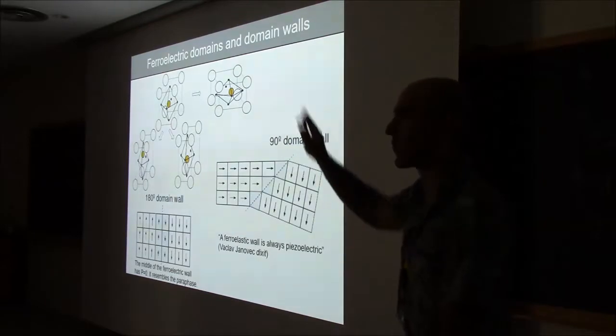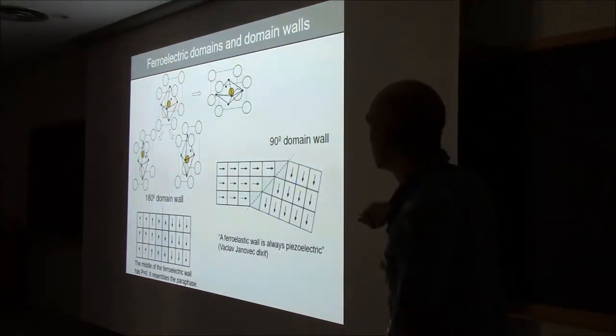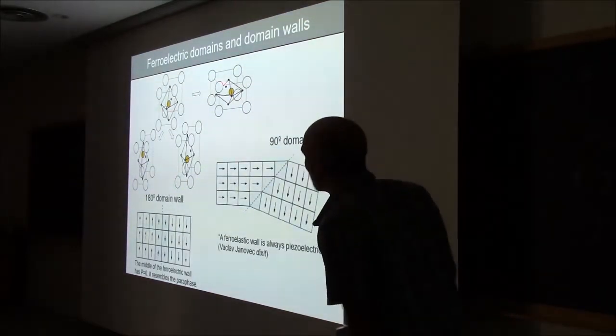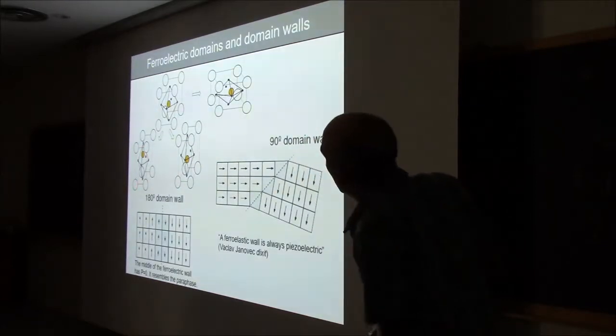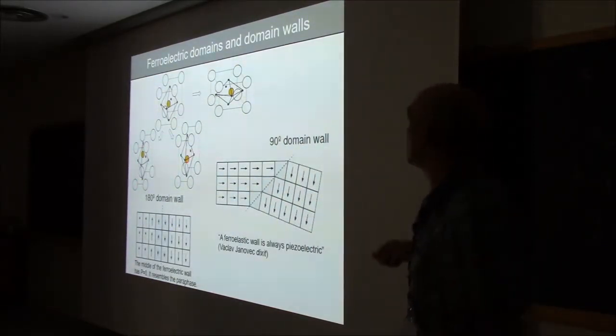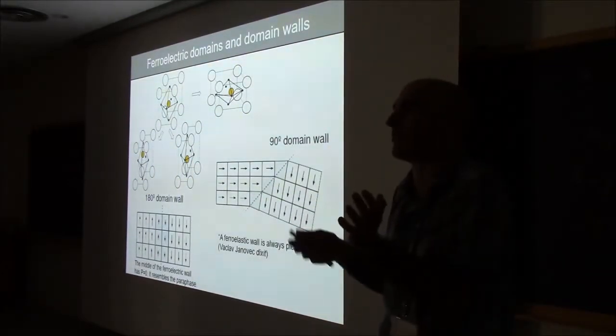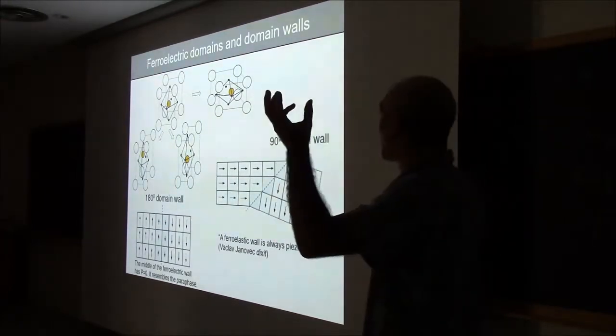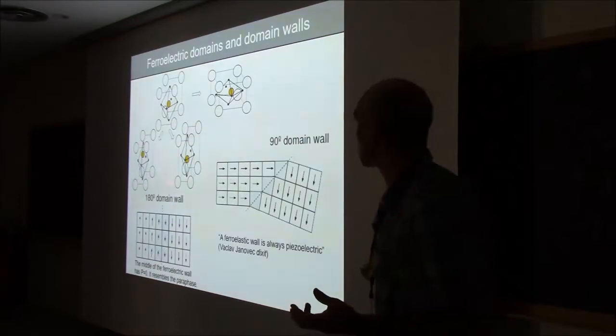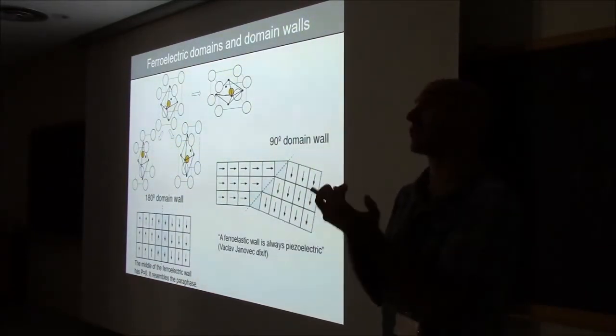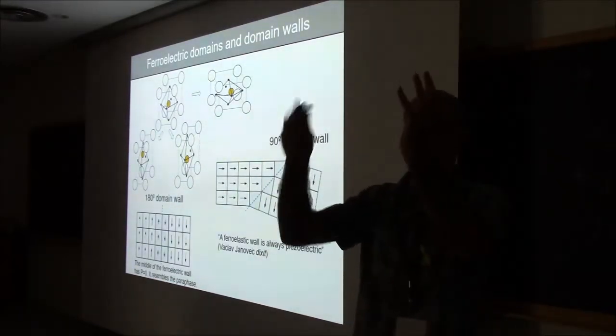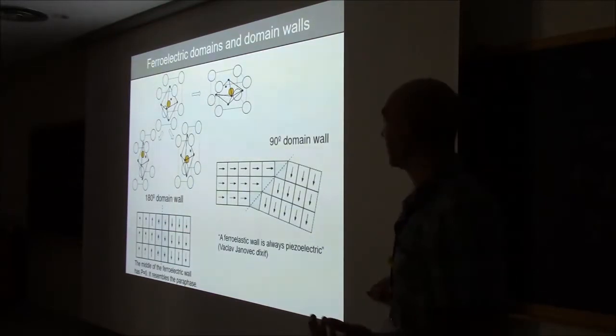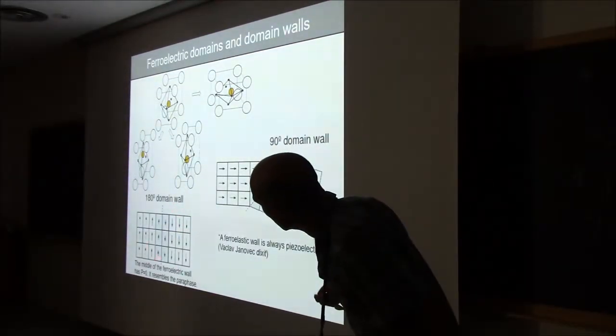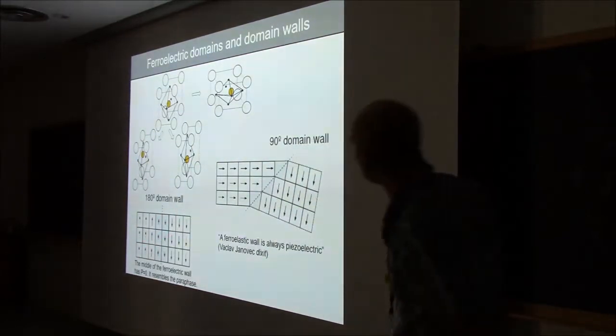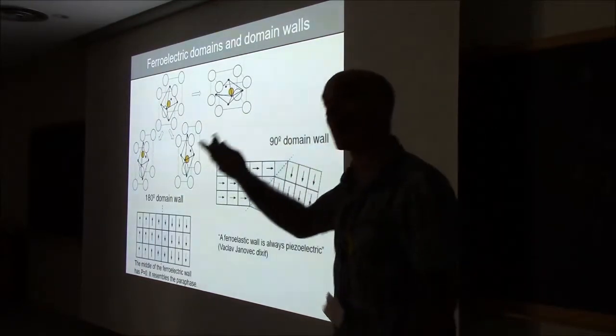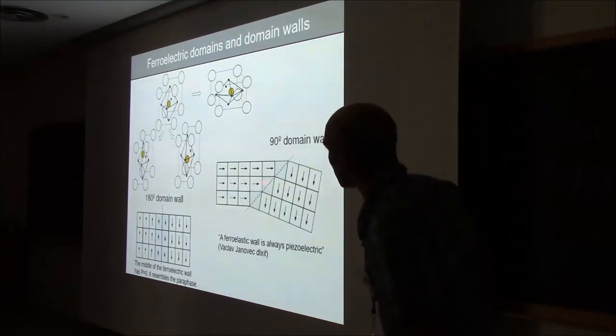if you take the simplest possible ferroelectric structure, going from the cubic state to the tetragonal state, you can go tetragonally horizontal, or tetragonally vertical with polarization up or polarization down. All of these are equally probable. They have exactly the same free energy. And if they have exactly the same free energy, when you cool down from the non-polar state to the polar state, you will have some regions like this, some regions like that, and some regions like that. And wherever they meet, that's called a domain wall. So a region that is homogeneously polarized is a domain, and where a domain meets a different domain, you have a domain wall. This is a purely ferroelectric domain wall, where the polarization is switched by 180 degrees. This is not just a ferroelectric but also a ferroelastic domain wall, where the vertical polarization meets the horizontal polarization.